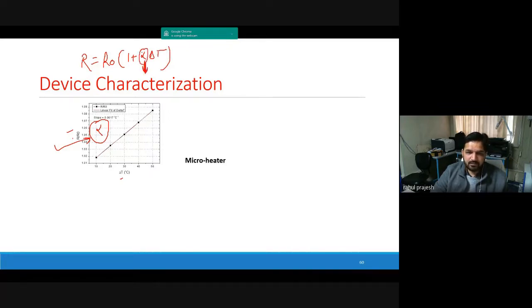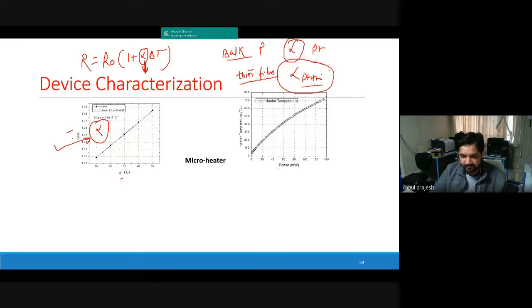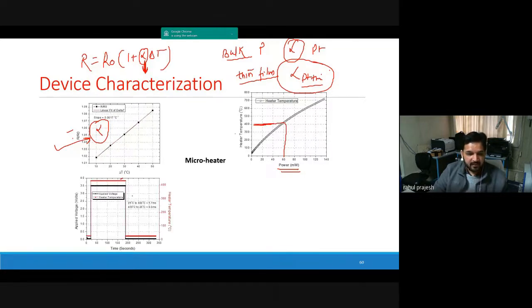Okay, you can take it from literature also, but experimentally you should calculate it, because sometimes what happens, the bulk material have different properties and thin films have different properties. So the alpha for bulk of platinum will be different from alpha of platinum of thin film. So that's why you should calculate the alpha first, and based on alpha you can calculate the temperature in the later case. For different powers you can calculate the temperature. You see over here 60 milliwatt is giving you 400 degrees centigrade. Then you calculate the rise time and fall time of the device, response and recovery time of the device. Here you see it's quickly heated up to temperature 430 degrees centigrade.